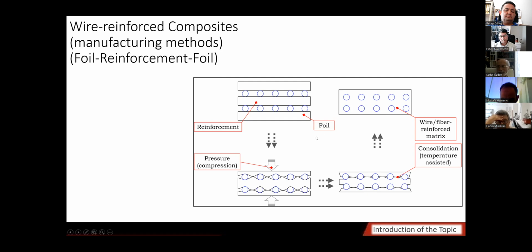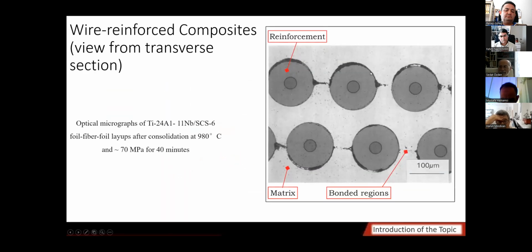Yes. Go on. But if you look at this image, you see that the thickness of the foil is not actually foil. This is a matrix form, but because the literature-active term used for that is foil, I have used foil. But actually, I was also thinking that it is not a foil. Okay. I agree with you. So here is an example from the literature in which wires are used as reinforcement, and here the bonding has partially occurred, not completely, and this titanium is working as a matrix.